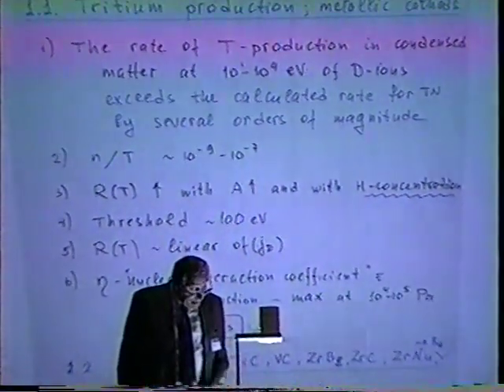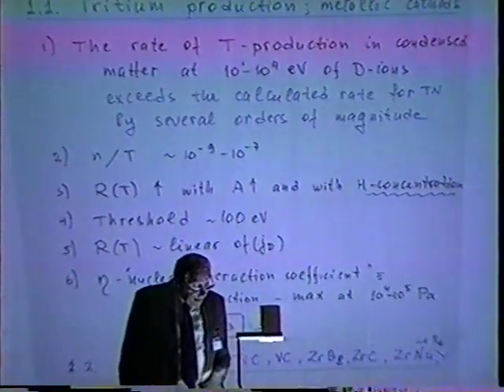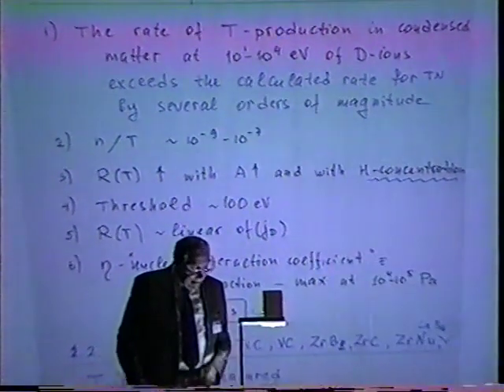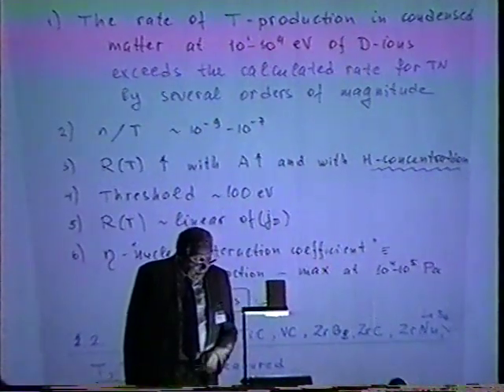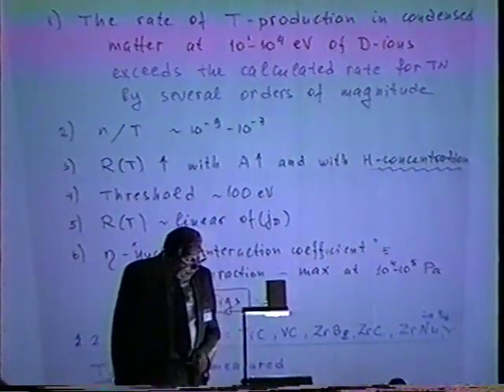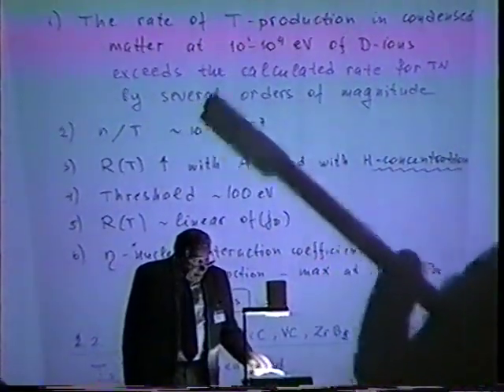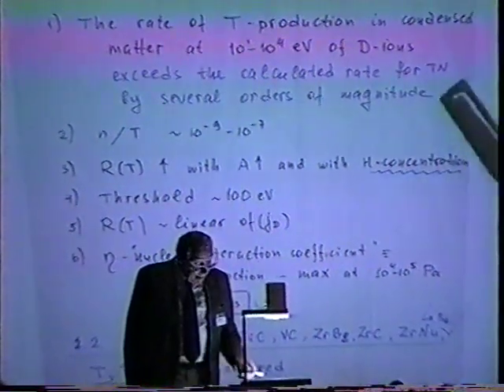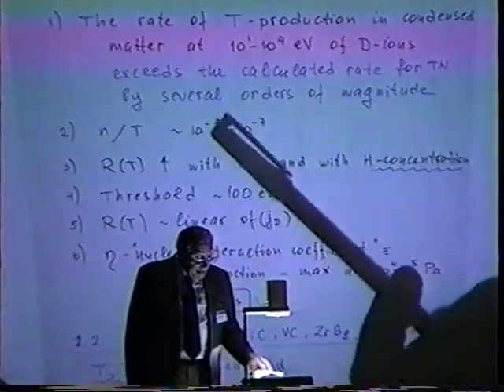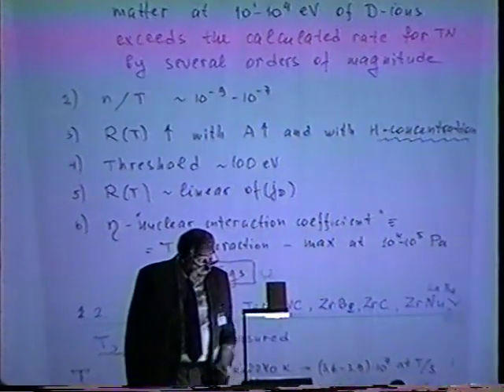First, they observed that the rate of tritium production in condensed matter at a voltage of about 10 to the 4 electron volts of the deuterium ions exceeds the calculated rate for thermonuclear reactions by several orders of magnitude.